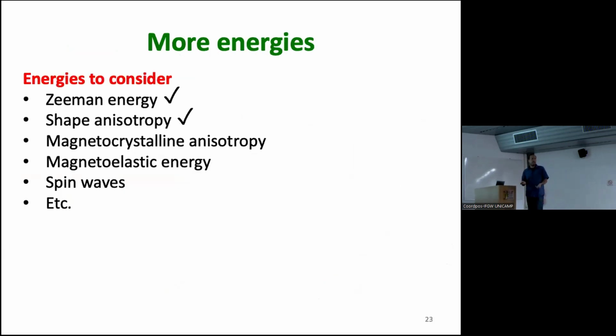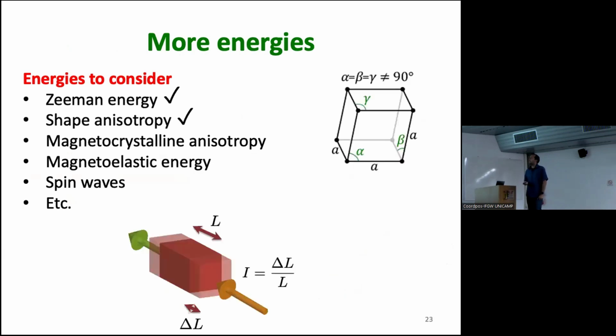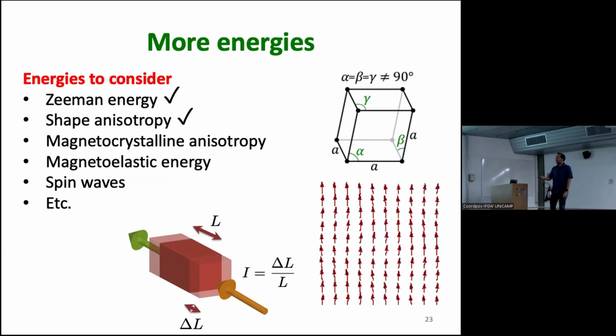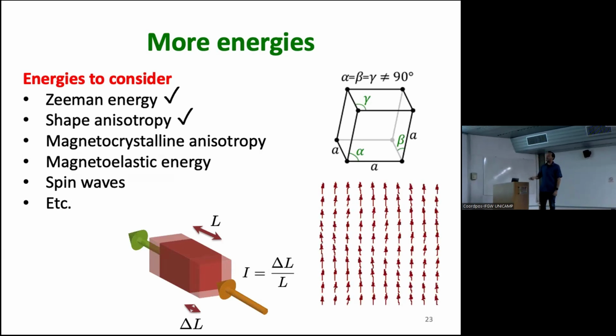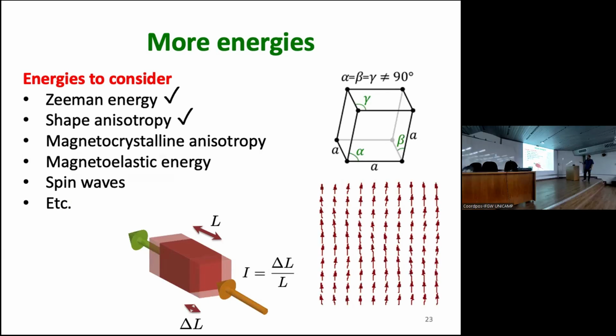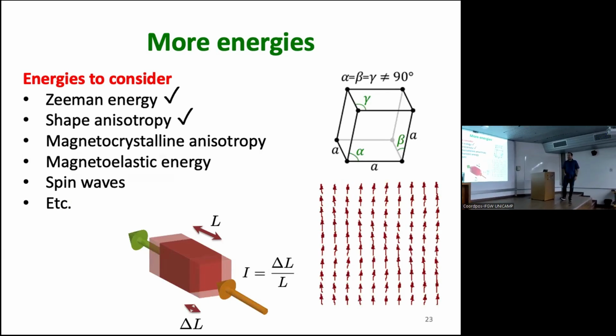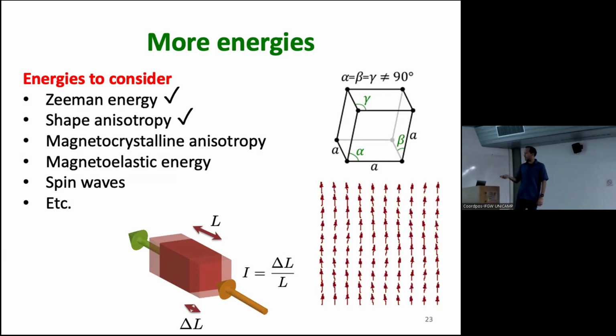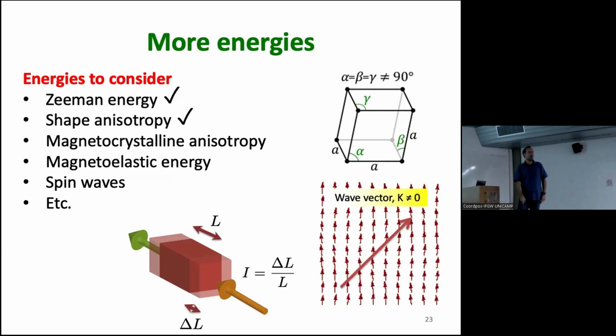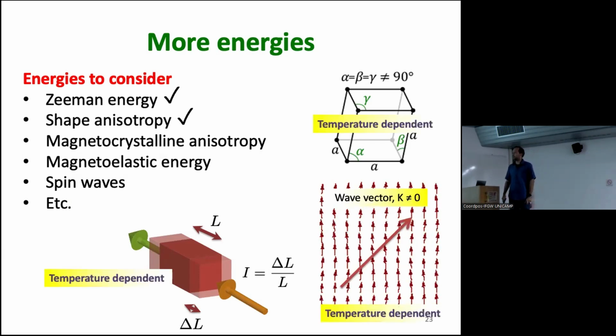So you can put all these energies into your free energy equation, and then you can see the effects of changes in the crystal structure, the crystal field, for instance. If I take a ferromagnetic metal and then I deform it, if I compress it or expand it, the magnetization will change. And I can see those changes also because the resonance field will change. And more interesting is that you can even see magnons. You can see how these other spins change, or the coherence between the neighborhood, and then you can see that there is a spin wave that is traveling in this direction. Okay, so all these things can be learned from FMR.